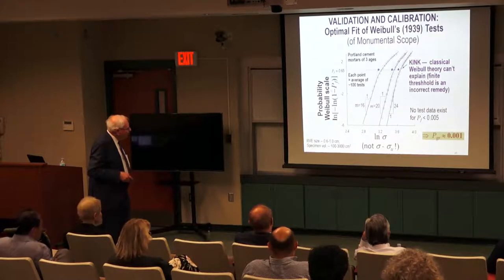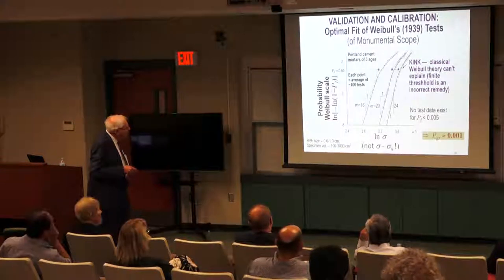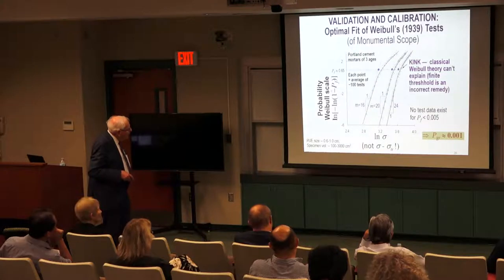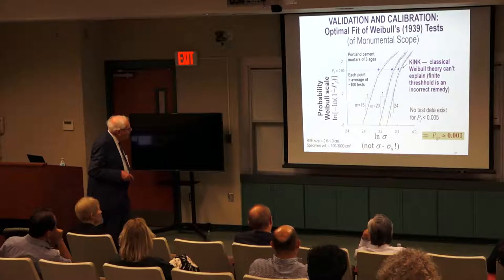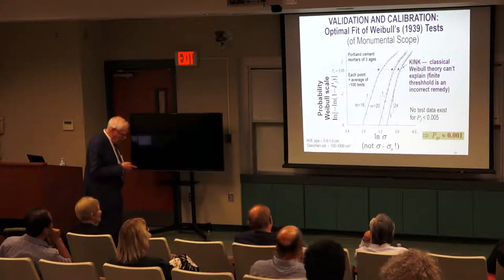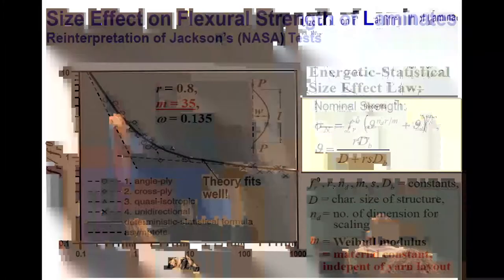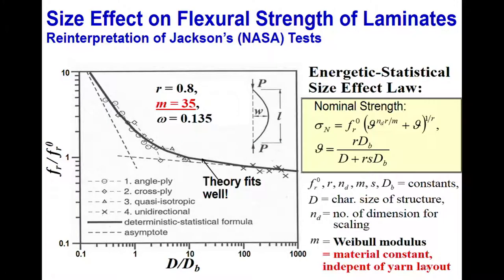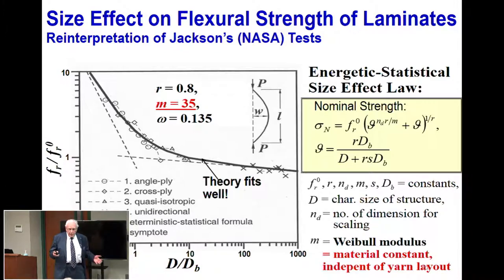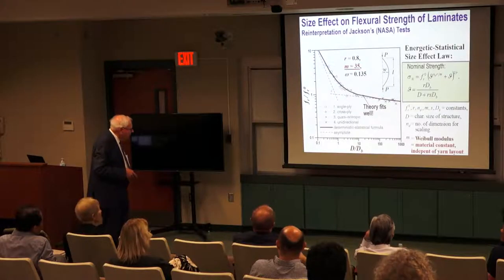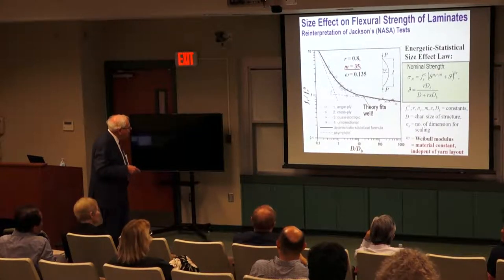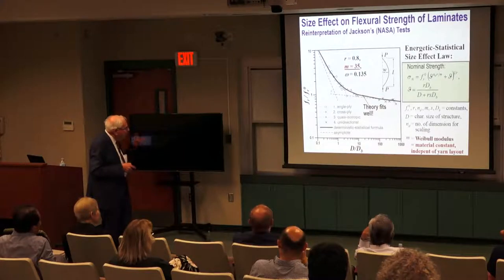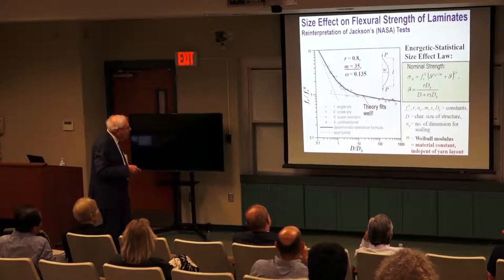Also here, we verify that the transition, which occurs from the size effect, you get at this point, and we plot it perfectly. People try to, the fit improves if you put in a threshold. In fact, Weibull pointed it out himself, but you fit it a little bit and then it does not work anymore. This is a set of composites from NASA, where they concluded in this testing by Jackson that the Weibull modulus is variable, that it depends on structure size and structure shape. Impossible, that's a material property. That's denying even the boundary value problem and so forth. Of course we have to normalize for different materials, which have different constants here, but it perfectly agrees. I don't say it proves, but no disagreement. We can perfectly fit all this with one Weibull modulus and with zero threshold. And you can even find a formula, an asymptotic matching formula, which describes that.